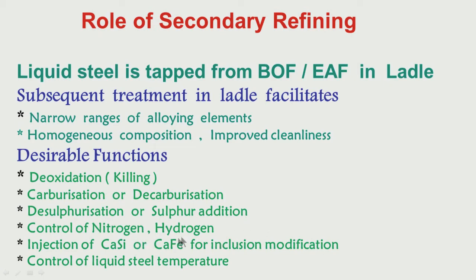Then control of gaseous elements like nitrogen and hydrogen in liquid steel. This is done through degassing. I will come to this in detail later on. Then maybe injection of CaSi or CaFe. Basically, injection of calcium helps in inclusion modification, making the inclusions liquid at steelmaking temperature, and it is easier to float them up and get absorbed in the basic slag. And finally, control of liquid steel temperature. This is essential if you want to do good casting.